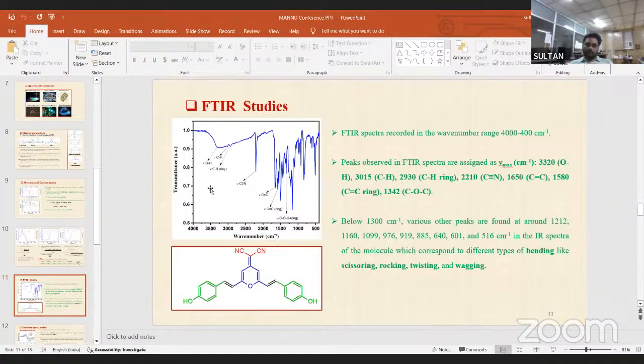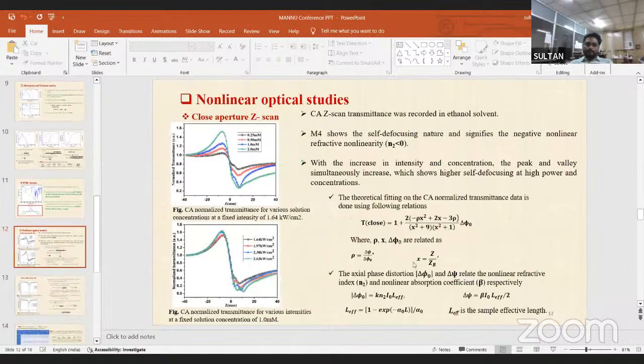And we found various absorption peaks below 1000 centimeter inverse due to different types of bending and deformation, like bending, scissoring, rocking, twisting, and wagging. For measuring the nonlinear optical property, we recorded the closed aperture Z-scan transmittance at various concentrations and powers. The theoretical fitting is given by this equation.